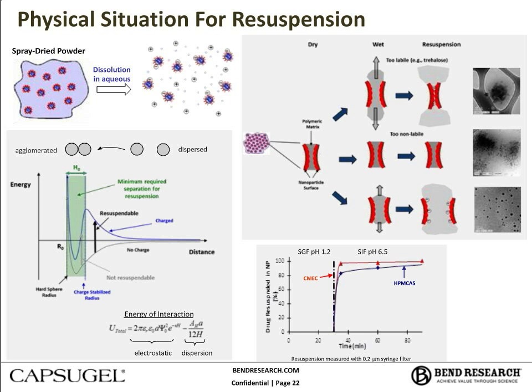What we found is that the small, highly water-soluble molecules, such as simple sugars, often are not the most efficient for suspending the particles because those materials tend to wet and dissolve quickly, leaving behind some stranded aggregated nanoparticles. And this is shown schematically in the first row of the upper right image in this slide. And there's an associated TEM image showing the aggregated nanoparticles resulting from a trehalose matrix, for example.